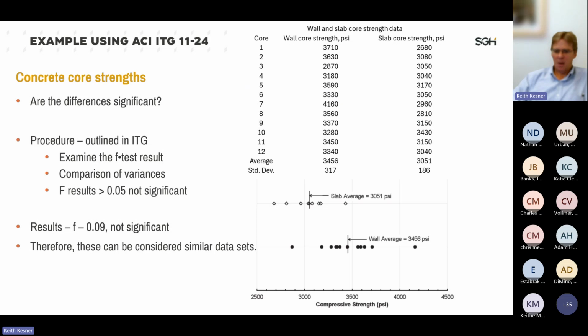So just as a quick example of what's in there, taking a look, we have data sets shown in the upper right, 2 different sets of core strengths. There's a slight difference in the average of the wall versus the slab core strengths, slightly higher, with a slight difference in the standard deviations. Are these differences statistically significant? So there's an actual procedure outlined in the ITG where we're evaluating using what's statistically termed the F test, which is a comparison of variance. And if your F test result is greater than 0.05, it's not significant.